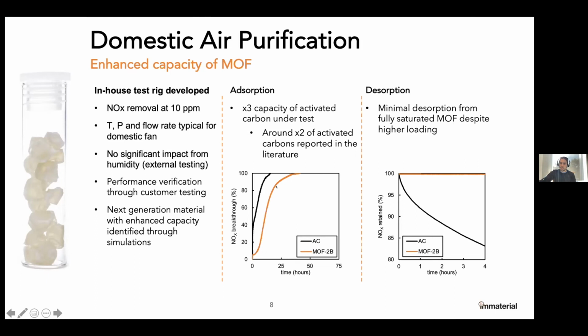So once these materials were saturated, we then just switched to running clean air through, and you can see that the activated carbon quite quickly gives off a reasonable amount of the NOx that it had previously absorbed, and in contrast, that is very much trapped within the metal organic framework. And that's despite the fact that it's been saturated with 3 times the NOx in the first place.